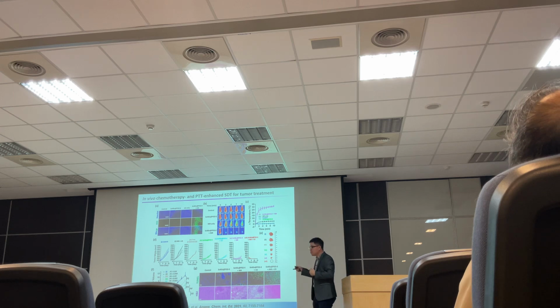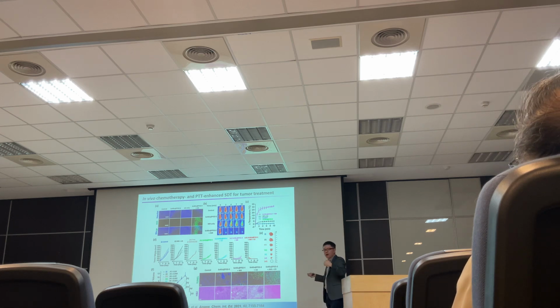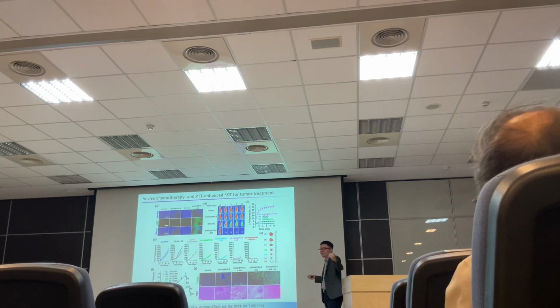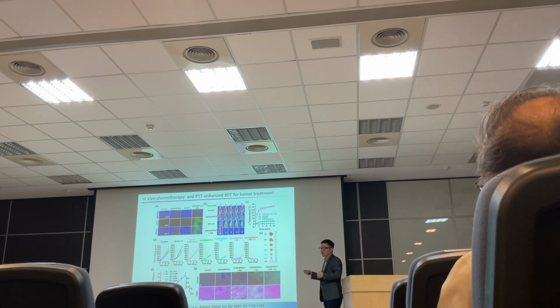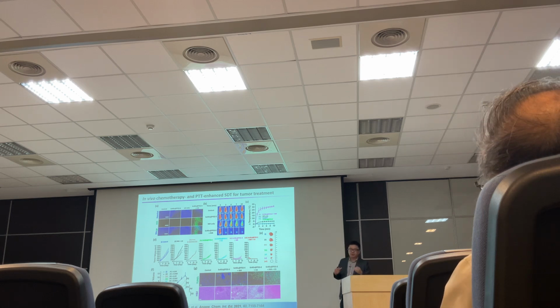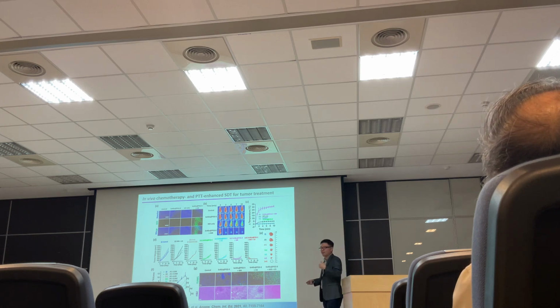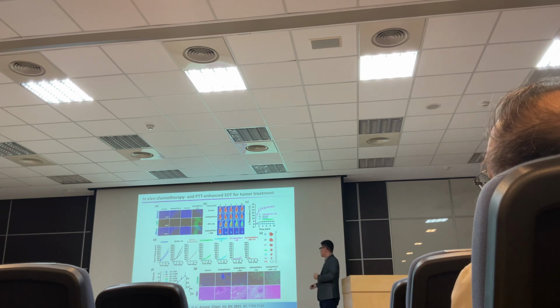And of course, we use tumor growth curves to validate our finding. In this group, we inject our drug-loaded nanoparticles, and we apply the ultrasound and the near-infrared. As you can see here, the tumor growth significantly drops to almost zero compared with the control groups. So this study means that we can use one particle, with ultrasound and near-infrared irradiation of the tumor, to achieve trimodal combination cancer therapy with synergistic anti-tumor efficacy.